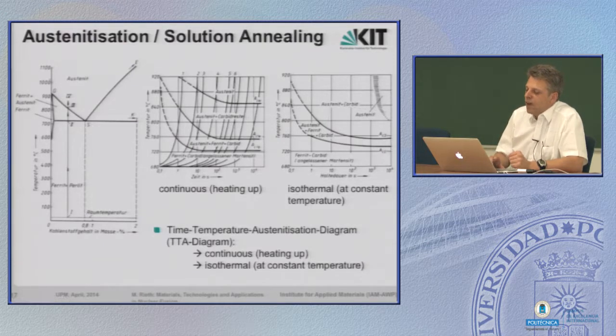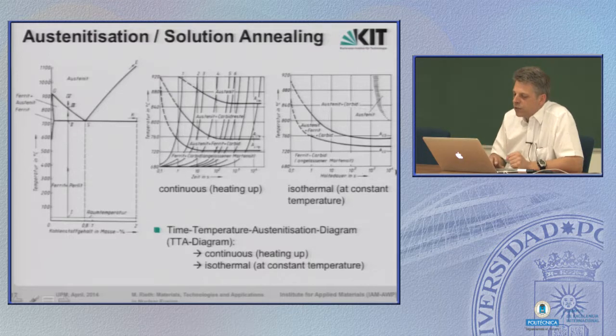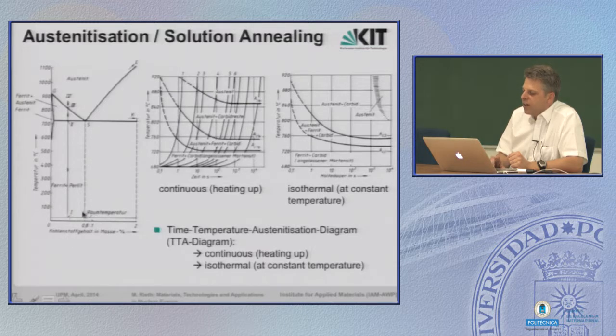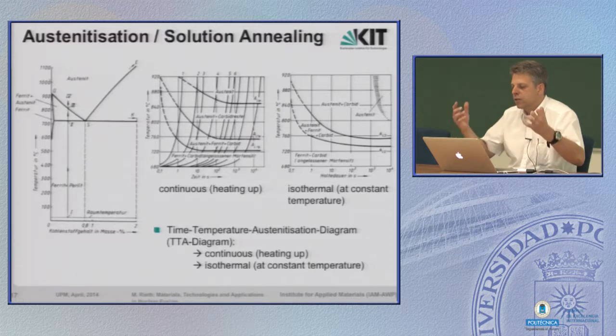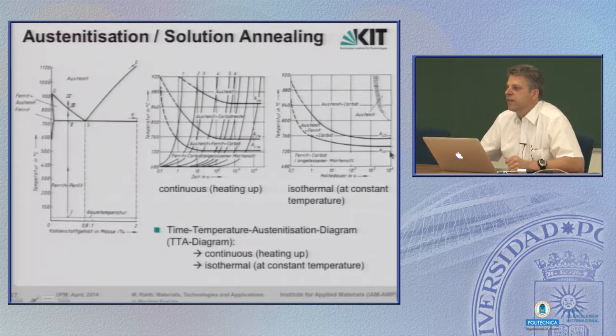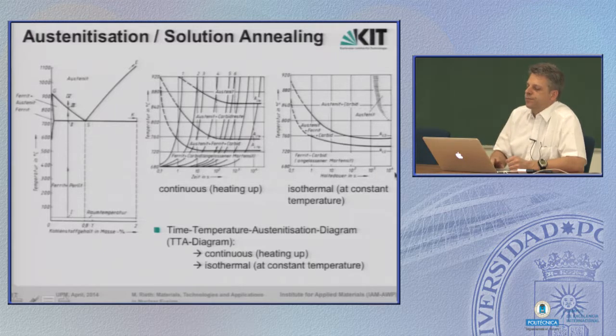So usually you do this not by heating up. Normally you take a piece of steel, put it in a furnace at one and the same temperature. That's an isothermal heating. So in an isothermal diagram, you see how long it takes until your material, when you start from ferrite and pearlite phase, until a complete dissolution or solution into austenitic phase has happened.